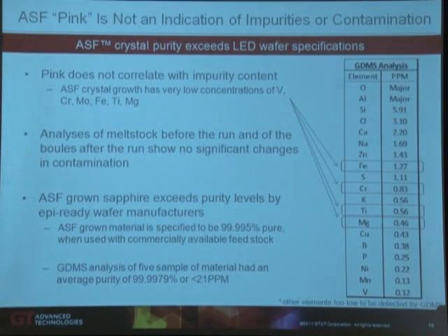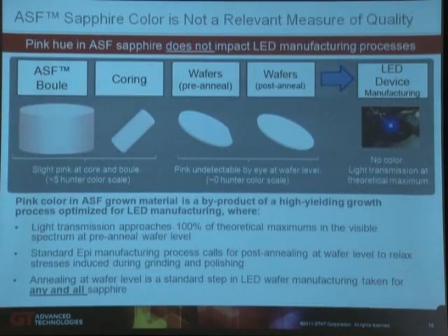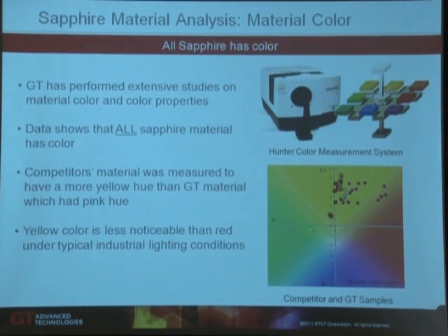So if you look at this, this is the sample set, again using the same sample set that we used in the wafering yield study. It was a blind sample. We had our certified technician use metrology equipment to actually measure the color. You can see this is ASF on the pink side, and this is the other competitive material and competitive growth technologies of the yellow.